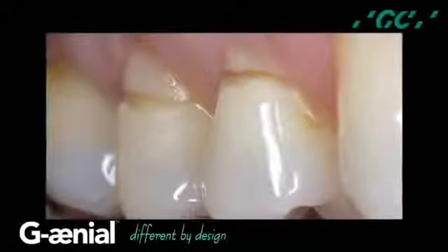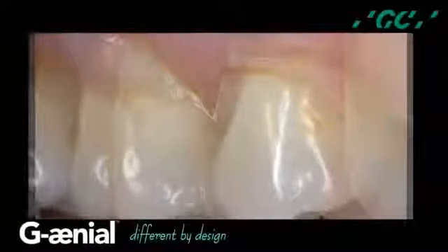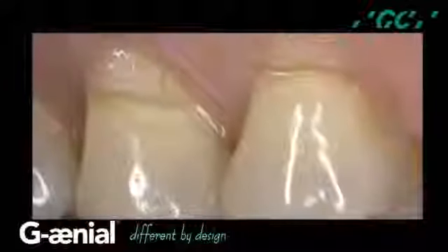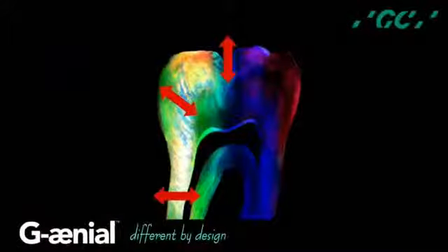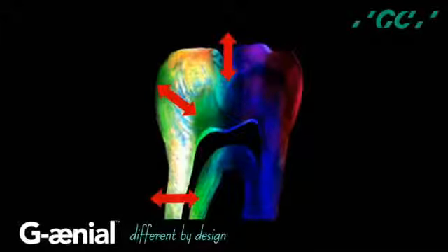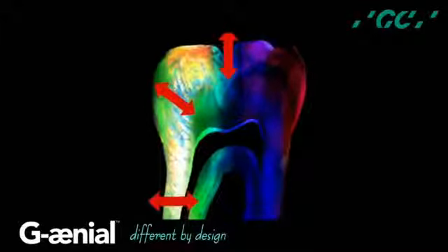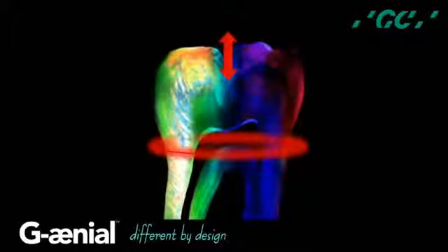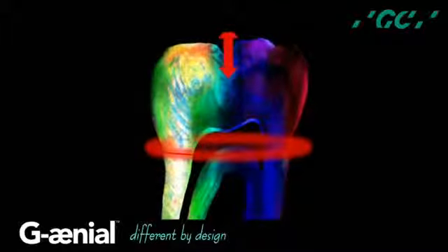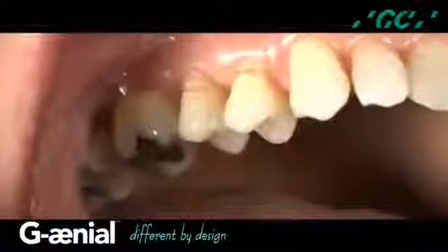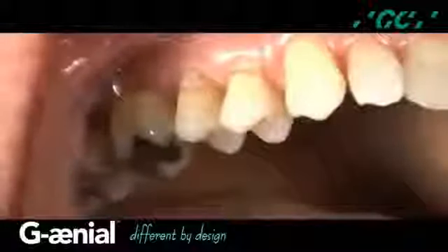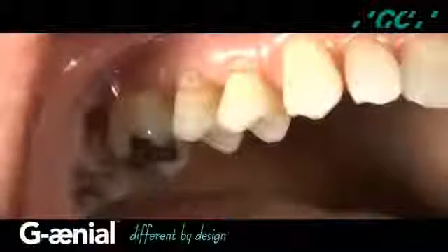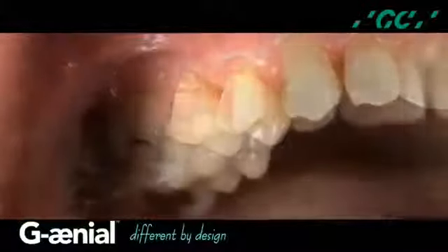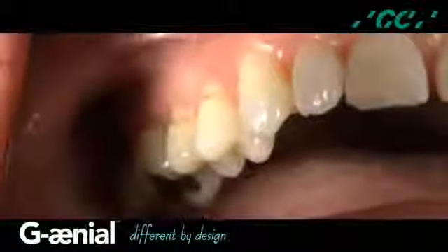Preoperative view of defective composite restorations on the maxillary right premolars. In the restored tooth, for cervical restorations, lateral flexure resulting from eccentric forces produces tensile stresses at the marginal interface of the restoration, whereas heavy eccentric forces generate compressive stresses along the marginal interface of the cervical restoration. These repeated flexural forces can cause adhesive failure of cervical composite restorations at the dentin resin interface, which can result in microleakage and partial or complete debonding of the restoration.